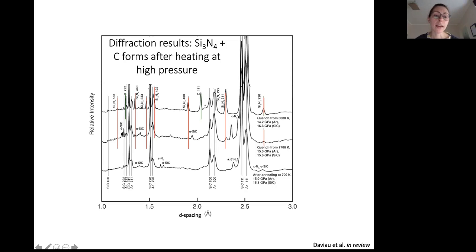And so these red barcodes highlight new peaks that are appearing in the patterns, and these correspond to silicon nitride. This is the cubic form, the high pressure form of silicon nitride, that we see coming up really strongly. And this corresponds to the disappearance of the nitrogen diffraction, as well as the appearance of carbon diamond. So what we're seeing is that the silicon carbide and nitrogen are reacting to form silicon nitride and carbon. So for these experiments, we do see a reaction.